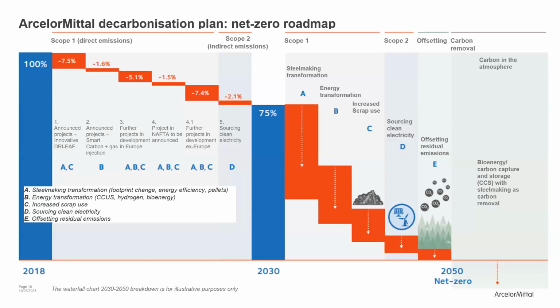Then under the third pillar, C, increased use of scrap. If you remember the orders of magnitude from the previous slide, you remember that the EAF route provides really low embodied carbon. And it seems quite logical: we need to recycle as much as we can. We need to leverage the scrap which is available to recycle the steel. Then pillar D is sourcing clean electricity, and pillar E, offsetting. As you can see on the slide, the offsetting comes at the very last. It is the lowest priority because we fully realize that it is the first pillars which are the most important and which practically will decarbonize our industry. Next slide, please.